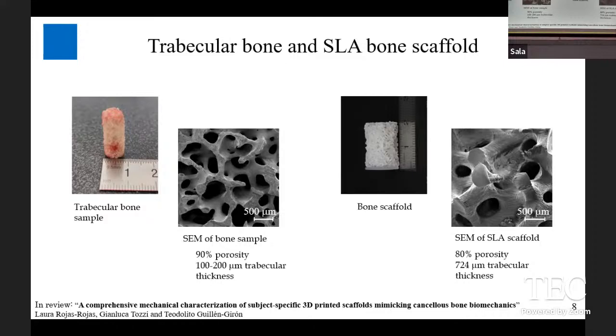However, as you can see, the trabecular thickness was a bit higher for our scaffold, but this was due to the printing technique that we used, the resolution that we couldn't achieve a one-on-one scaffold reproduction. But I think it's okay, because you can see there is a variety in the trabecular thickness. Not all of them are the same. These two characteristics, porosity and trabecular thickness, are very important in bone because they determine their mechanical properties.